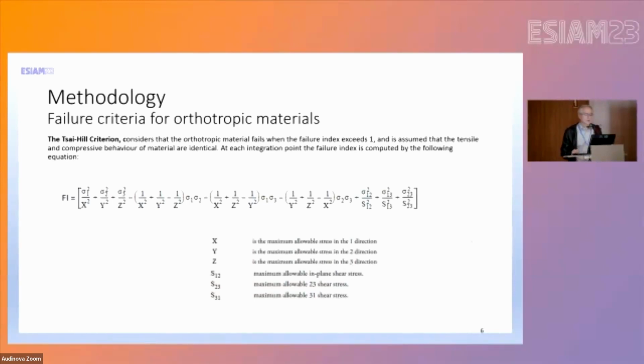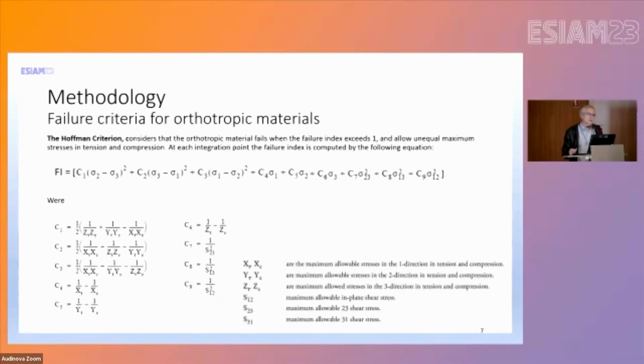The Tsai-Hill criterion considers that the orthotropic material fails when the failure index exceeds 1, and it is assumed that the tensile and compressive behavior of the material are identical. The failure index is computed using this equation. The Hoffman criterion is similar to the Tsai-Hill, but allows unequal maximum stresses in tension and compression. The failure index is given by this equation.